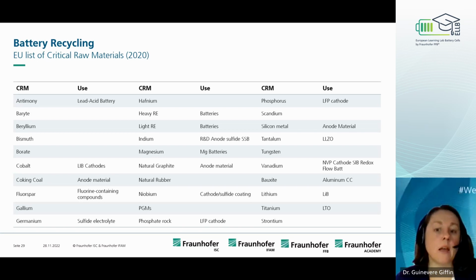So the cobalt is clear. Fluorspar appears again. However, there's also things like the research materials used for solid-state batteries, indium with sulfides. Niobium is often used as a coating for cathodes in combination with sulfides. Tantalum with LLZO, an oxide-based solid-state electrolyte. And then you can even start to see things that could possibly play a role for sodium-ion chemistry. So for example, vanadium, NVP or sodium vanadium phosphate is one of the sodium cathodes that's being investigated at the moment. Also here, vanadium for redox flow batteries. And so the point is, in general, raw materials are definitely an issue.